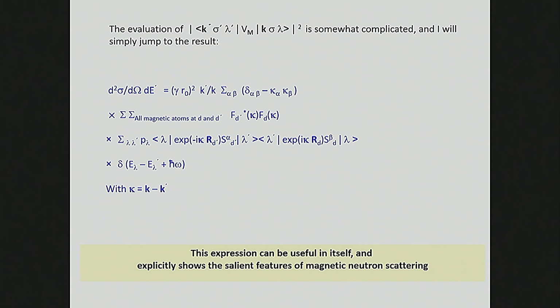And then our experiment is going to depend on the magnetic form factor of the atom that's doing the scattering. So this is the equivalent of this: for phonon scattering it was that Q dot eigenvector squared. And the Q dot eigenvector squared was the term that let us distinguish between a longitudinal phonon and a transverse phonon.